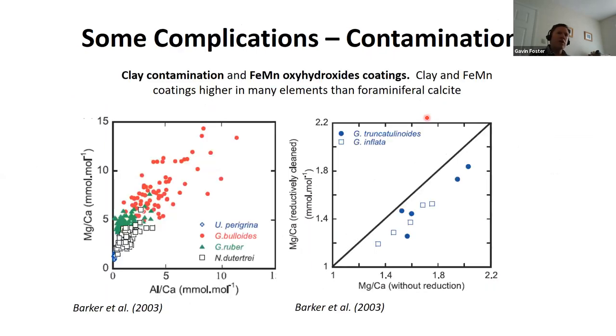So when we're measuring the trace element composition of these foraminifera, I've expressed it here in micromole per mole, but this is a hundreds to thousands of ppm level for magnesium, down to levels of about a ppm for some of the other elements. So that's the range that we're interested in. And because of that, we run into problems where we get contamination from other sources or other things in the sediments. So when the forams sink through the water column, they get coated with iron manganese oxyhydroxides,